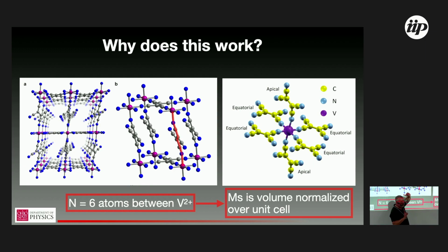And so that order is going to be quite robust. But then the magnons interact through both exchange and dipole fields. Sure. And so they care about the total volume density of the spin. And these large pores strongly suppress that volume density, which means that the exchange stiffness, basically how easy is it to rotate adjacent spins as you move down the line, is quite floppy, because the spins are moving into this empty space with no other spins to push back against them.